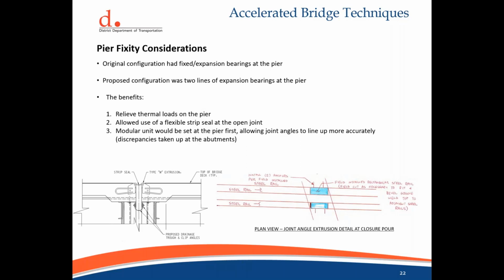First and foremost, we wanted to relieve some of the thermal and longitudinal loading on the pier. As John had mentioned, the substructure rating was less than 1, so we really wanted to get the loads down. The expansion bearings at the pier allowed us to do this. Secondly, a strip seal joint could be used for the drainage, similar to the as-built condition.